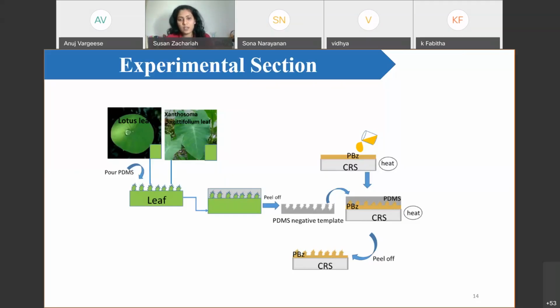Once it is cooled to room temperature, it is peeled out so that we get complementary structures of lotus and Xanthosoma sagittifolium leaf. You can find the lotus leaf having peaks, and it has complementary holes on the PDMS negative template. On the other hand, I took the cold rolled steel, cleaned it properly, and poured the polymer solution, which is polybenzoxazine in NMP, and this is coated over CRS.